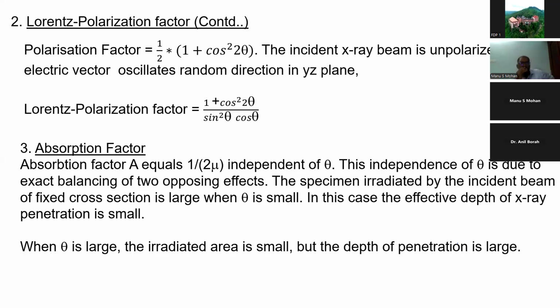We can resolve the electric vector and find out its influence on intensity. The Lorentz polarization factor, taking all these factors together, is (1 + cos squared 2theta) divided by (sin squared theta times cos theta). Basically, it is dependent upon the Bragg angle, giving an intensity quite different from the contribution of structure alone.